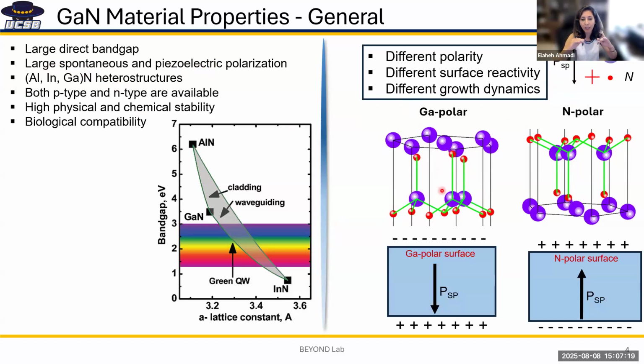Now, nowadays almost all the optoelectronic devices are made on gallium polar. If you look at the crystal structure of gallium nitride, because of this asymmetry, the polarization is opposite on the two sides: one side is terminated by gallium atoms, and if you flip it and look at the other side, it's terminated by nitrogen atoms. These two surfaces have different polarity, but also different surface reactivity, and the growth dynamics of these two are very different. Now the devices that we see, like the gallium nitride HEMTs in 5G base stations, and most of the blue LEDs that are commercially available, have been fabricated on this gallium polar side.